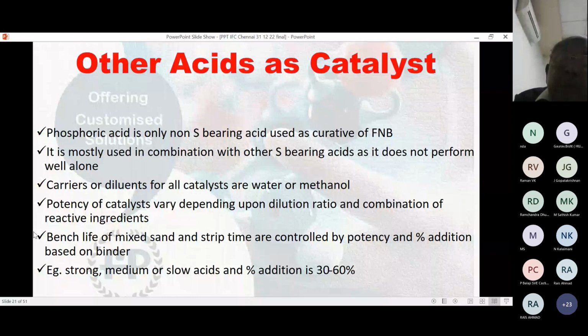But there is an upper limit of dilution. That means you cannot make it 90% because at this it reaches the saturation point of the acid and it precipitates. So in most cases, the upper limit is not more than 75%. Then apart from this dilution, you can control by addition from 30 to 60%. So there are two variables for you. One is the dilution ratio of active component and your carrier, giving a strong, medium or slow acid, and then percentage addition, which is 30 to 60%.